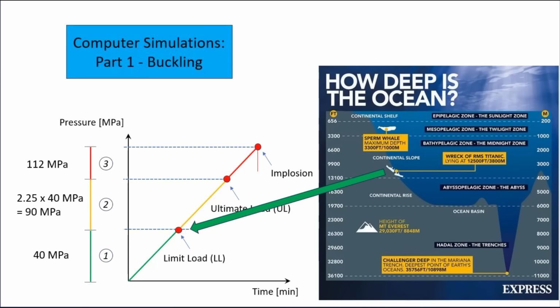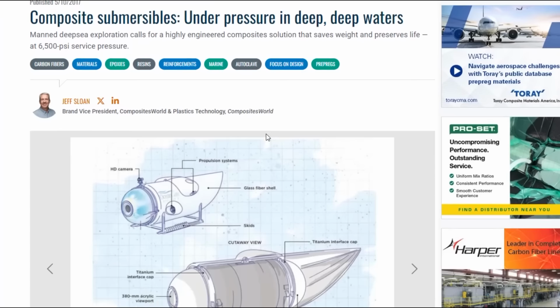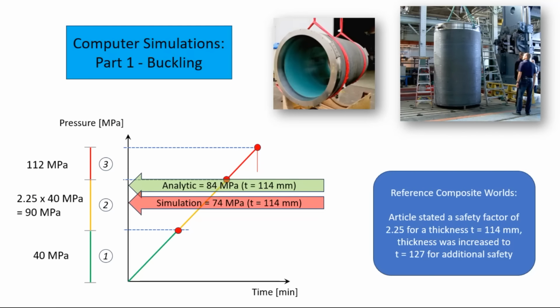The ultimate load is the product of limit load times a safety factor, which was 2.25, according to an article in Composite Worlds. The Composite Worlds article stated that a safety factor of 2.25 for a thickness of 114 millimeters was established for the CFRP cylinder, but the thickness of the CFRP cylinder was increased to 127 millimeters for additional safety. However, the results of analytical equation and simulation show much lower loads than we would expect.